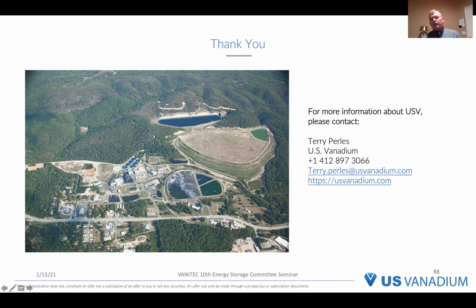Well, I will say that we consume about 5.5 metric tons of vanadium for every megawatt hour, or 5.5 kilos of vanadium per kilowatt hour. Some of the battery guys may have slightly different numbers depending on the utilization rate, but we're talking about 5.5 kilos of pure V, or about 22 pounds of V2O5 for each kilowatt hour.